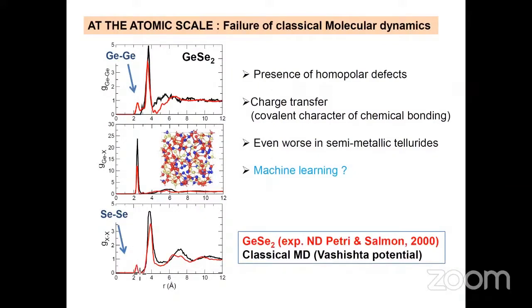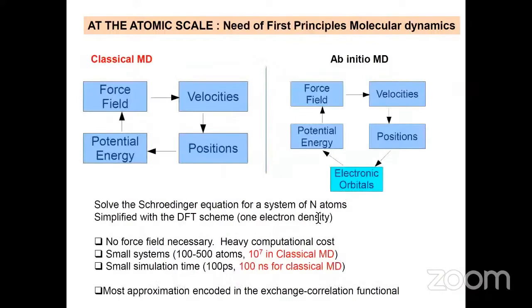Furthermore, you can't deal with the charge transfer, which is typical in covalent character of the chemical bonding that you encounter in those chalcogenides. And of course, one expects it becoming even worse in semi-metallic tellurides. I should briefly mention that there may be alternative paths to ab initio simulations like machine learning, and there are very recent efforts on this kind of topics. So basically, we want to use ab initio MD.